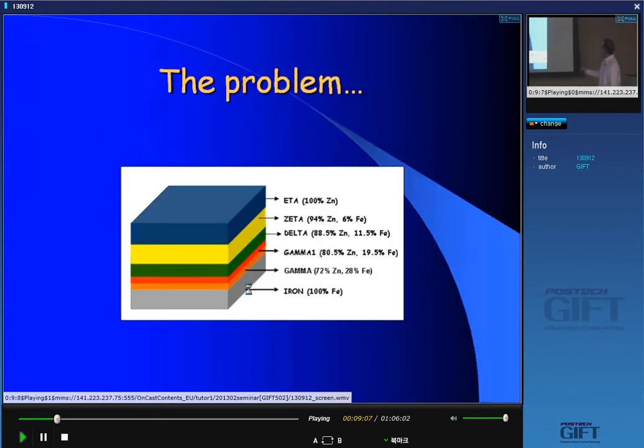Now, let me go back to the previous slide for 1 minute. Now the question is, if we apply a shear force, normally the shear force acts here on the top surface. But remember, there are several interfaces. So this force will slowly induce some kind of shear forces here, here, here, here, here. And since the material properties of all these faces are different, the level of shear here, level of shear there, level of shear there may not be the same. The question is, once I am talking about the best possible design of this material, which will fail after maximum energy and with a minimum deformation, that behavior has to be designed separately here, separately there, and so on. That means all the interfaces have to be somehow examined differently.